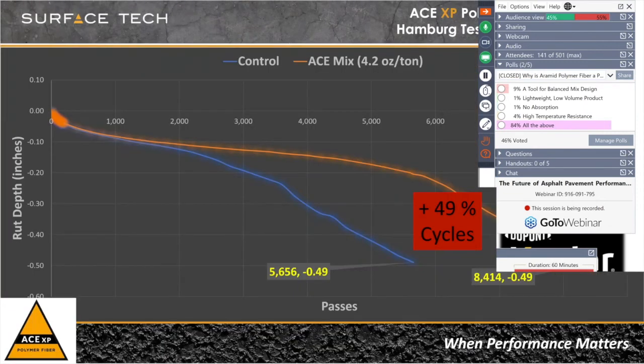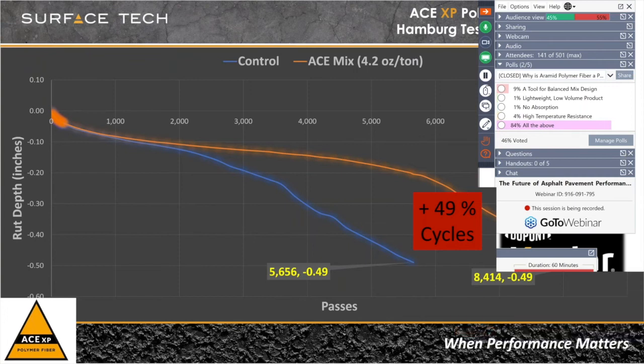And then we had a couple pilot jobs that went down in Texas back in 2016. In Texas, the paving contractors are all required to have Hamburg tests run on every mix design that they put down in the field, so on the mix that's coming out of the plant. And as you can see here, the ACE is in orange and the control is in blue. This was a 64-22. And lo and behold, to get to a minus half inch on the y-axis, or 12 and a half millimeters, we were actually able to provide that with almost 50% more cycles to failure.